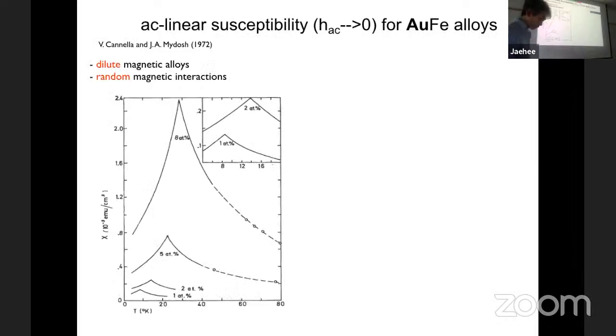For instance, back in the 1970s, spin glass was a very hot topic. So this is the ordinary spin glass. The system is the following. We have a non-magnetic metal. Then we dope magnetic impurities at very low concentrations. The interaction between these magnetic impurities is governed by long-range RKKY interactions, and the coupling constant varies as a function of distance. In fact, it fluctuates between positive and negative, antiferro and ferro, very randomly, because the magnetic impurities reside randomly.